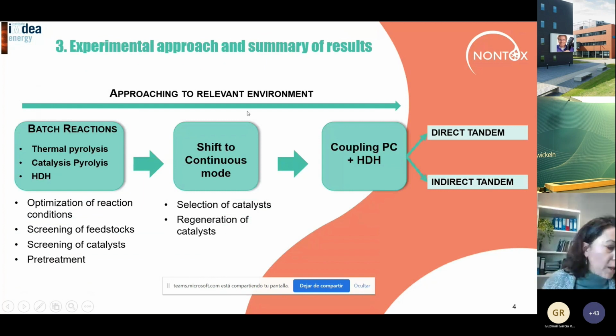So what's the approach that we applied in order to valorize these residues? As I mentioned before, we applied catalytic pyrolysis and HDH, hydrodehalogenation treatments, but this was performed following a step method. First, we carried out reactions in batch conditions in order to optimize the reaction conditions, to screen the different feedstocks and catalysts, even to explore the possibility of carrying out some pretreatments.